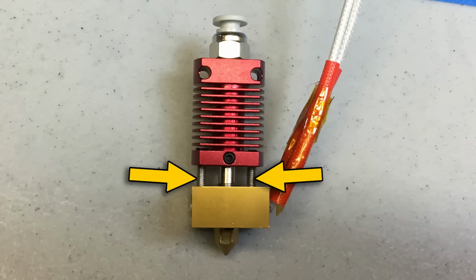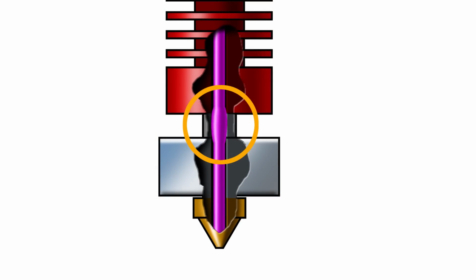What's happening is heat from the heat block is transferring up those screws into the heat sink. That's the part in red with the individual fins for cooling. That area is meant to be room temperature. When it heats up, it can cause the filament inside of it to reach its glass transition point and soften slightly. As you do retractions, it's going to stretch that filament out. When it pushes it back in, it's going to deform it. That is going to cause additional drag, which can cause underextrusion. It can also create a clog.